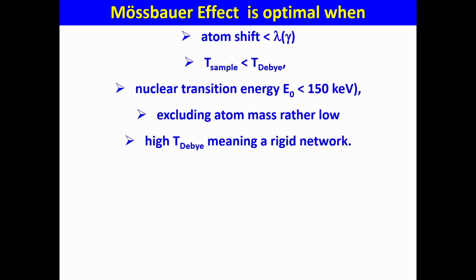Okay, so, conclusion. The Mossbauer effect is optimal if you have a small shift of atoms, much lower than the wavelength. If the temperature of the sample is much lower than the Debye temperature, as we were discussing, this problem of rigidity in terms of Debye temperature. Usually the transition energies are less than 150 kilo electron volts. It's difficult to see some effect when you have atoms with a very low mass, and we will see just after the possibilities by scanning the whole periodic table. And of course, we need a high Debye temperature.